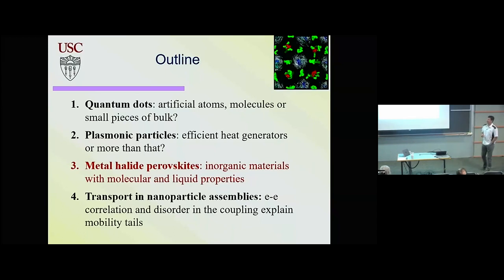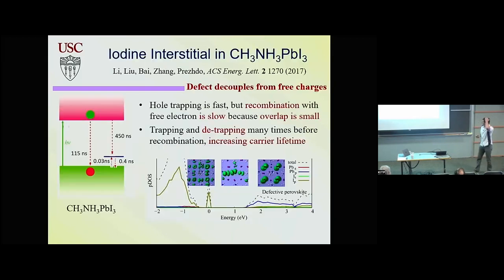When you can find them, you have efficient emission. So the main feature of this material, why they're efficient, is that defects are not bad. When we first looked at the material, we looked at two types of defects that are most common. You have this halide that can diffuse, and if it diffuses, you have extra halide interstitial, which is this example, or vacancy, which is missing halide.